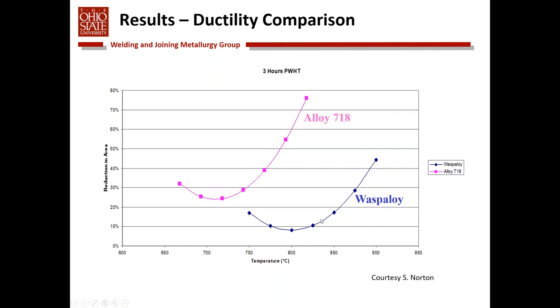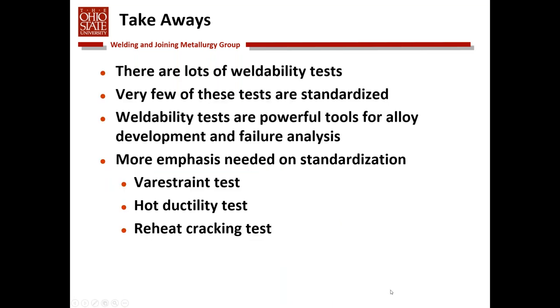And so what this test data shows us is that the drop in ductility, or the minimum ductility of Waspaloy, is below that of Alloy 718. Again, we know from experience that this alloy is more susceptible to post-weld heat treatment cracking than Alloy 718, and the test technique basically provides that information.